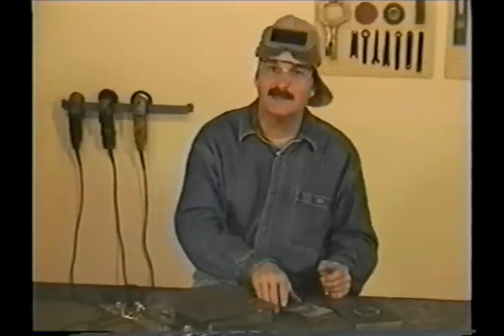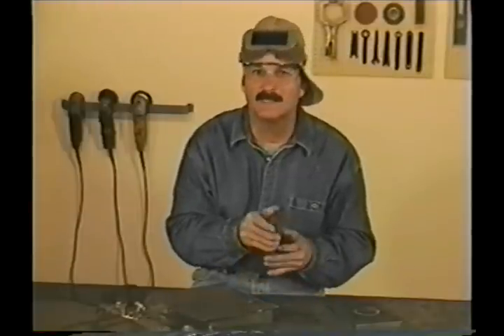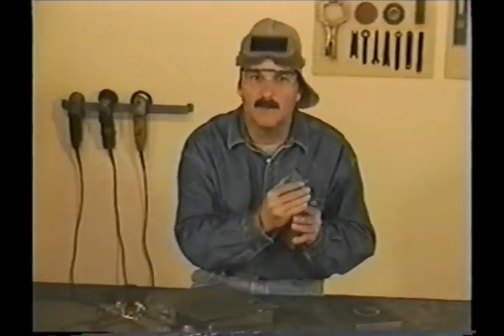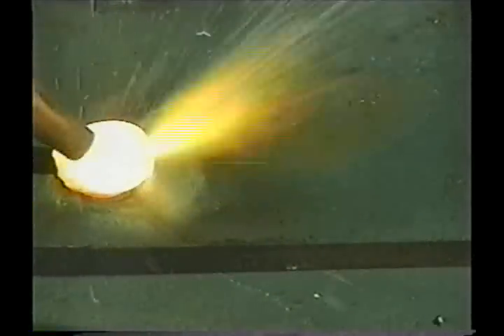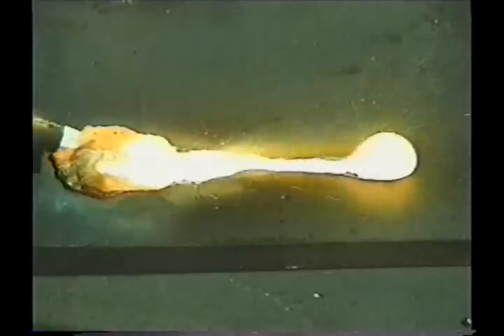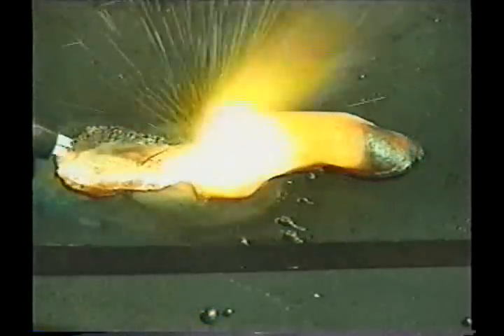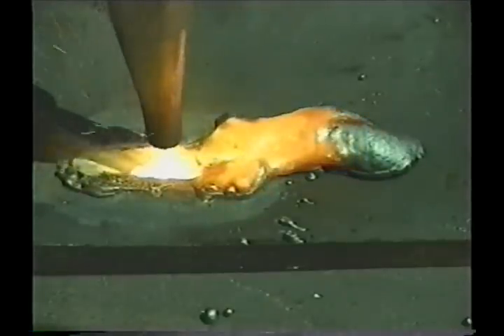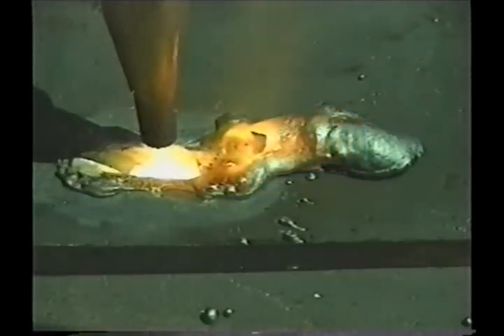Now, cutting torches like this don't like to cut through two pieces of metal at one time. Sometimes you'll get lucky, but most of the time, the second piece won't get hot enough, stopping the cutting jet from getting through, and the slag comes back up in the kerf. The best you can do is to angle the torch and wallow through the top piece, blowing out the slag until you can preheat the bottom one. And this is never pretty. When you're through the first piece and preheating the second one, you need to be careful the tip doesn't get so hot that it melts.